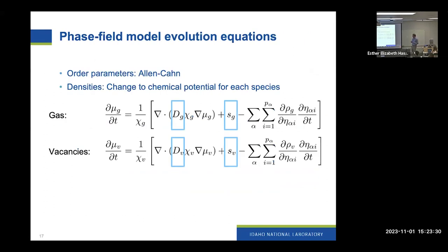So from that grand potential functional, we derive our evolution equations. For the order parameters, we have an Allen-Cahn evolution equation. And then in the grand potential formulation, rather than evolving concentration or density, we actually change to an evolution equation for the chemical potential. That's what's shown here, the chemical potential evolution equations. We have diffusivities that are informed by atomistic calculations. And then we have these source terms that represent the net production of defects.